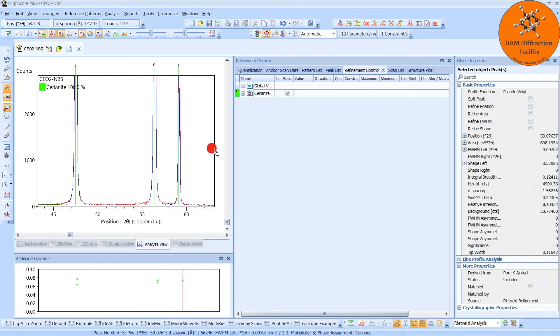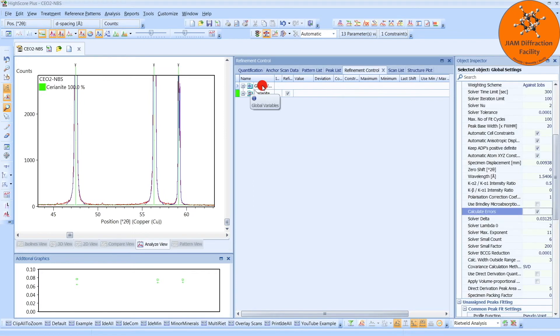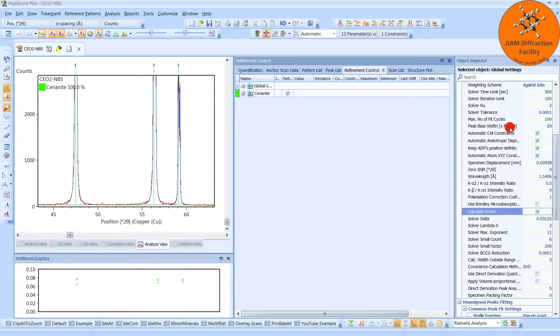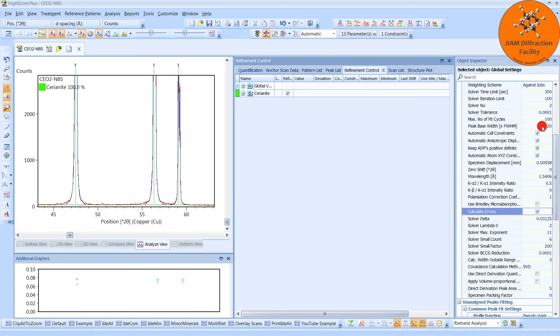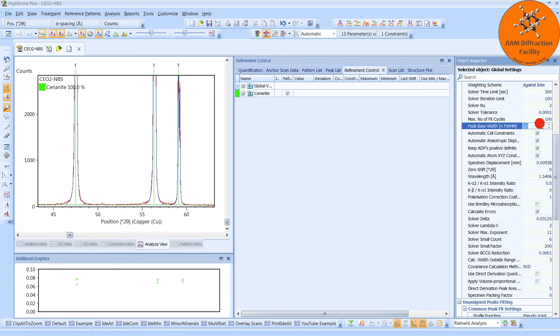This can be fixed by going to global variables and left-clicking. And the problem is with the peak base width, which is in multiples of full width half maximum. What this means is that if it is set to 20, then your peak base will have a width of 20 full width half maximums of that peak. So if, as in this example, we see the blue curve drop down too quickly, it is because this number is too small.